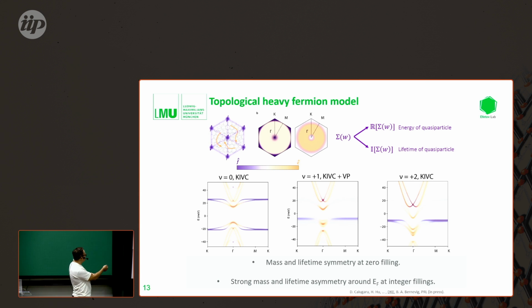And coming back now to the spectra that were calculated from the topological heavy fermion model, again, one of the advantages of this model is that it gives us the lifetime of the quasi-particles, right? So basically, the diffusion or dispersion that you can see here in the bands, this is directly reflecting the lifetime. So you see, the heavy bands are very, very broadened here.